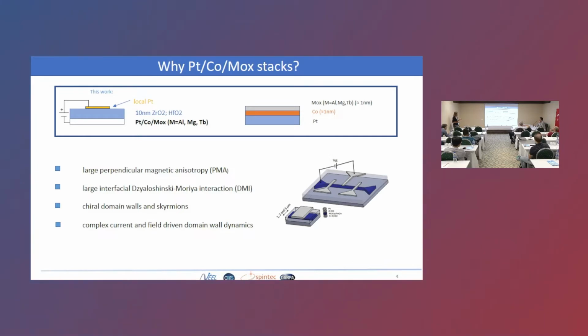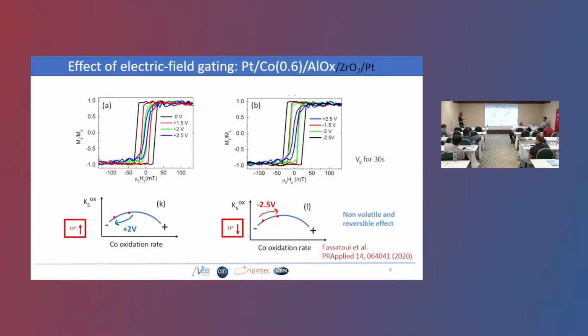So as I said, we start with platinum cobalt alumina, then we cover it, that is patterned, with 10 nanometers of zirconium oxide or hafnium oxide that are both well-known high-K dielectrics that are also good ionic conductors, and then we pattern platinum electrodes on top. Okay, so then I will show you some examples of the results obtained in the last couple of years.